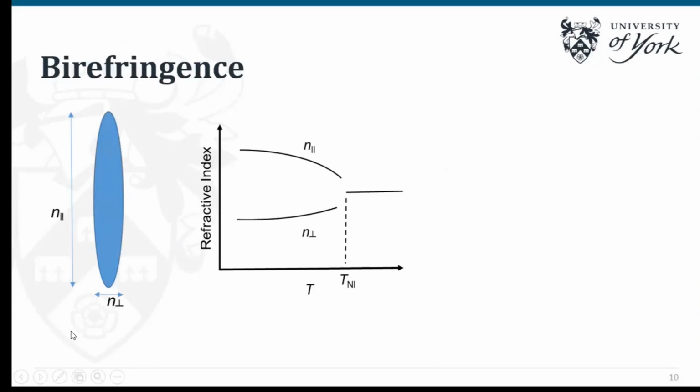Because the molecules and the phase itself are anisotropic, there are two refractive indices to the molecule: the ordinary or parallel refractive index and the extraordinary or perpendicular refractive index, which in the liquid crystal phase, because of the ordering, can act independently and can result in the splitting of plane polarized light, hence giving rise to double refraction and birefringence. But once you reach the isotropic liquid phase, they average out because the molecules are randomly ordered.